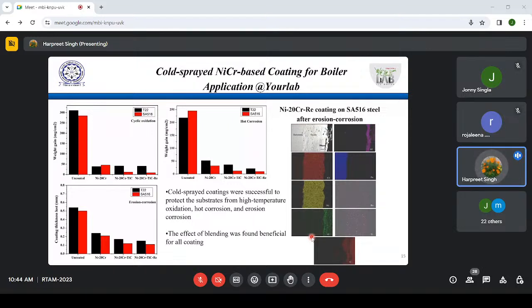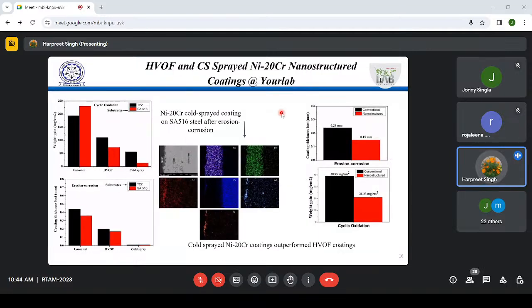Then this is another set of nanostructure coatings which we again developed at IIT Ropar itself. So again we could develop very nice coatings with nanostructures, right? And erosion corrosion was further decreased. This is a conventional coating which was developed by Neeraj Wala, but then Manoj did some nanostructure work, and then he could further improve the erosion corrosion resistance, right?